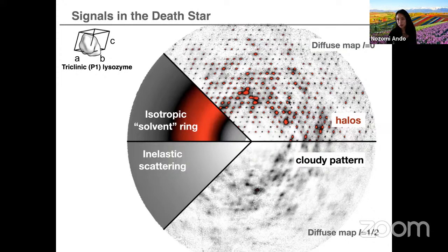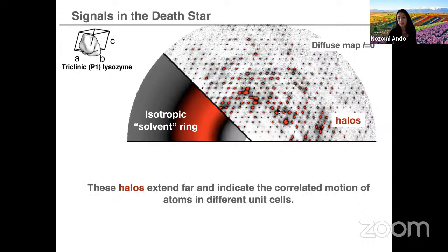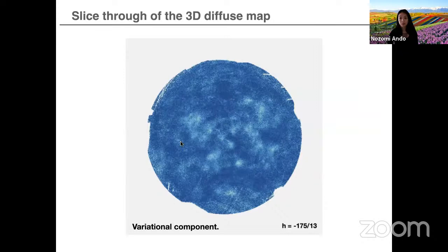Again, there's no more Bragg diffraction in here, yet we're still seeing things that look like Bragg diffraction. And not only that, but they extend far from where the Bragg diffraction is expected. And this is really a sign of some kind of translational disorder in the crystal. There's long range correlated motions. In other words, identical atoms in different unit cells are correlated. And that was really surprising. So that was the first thing that we saw with this finely sampled map.